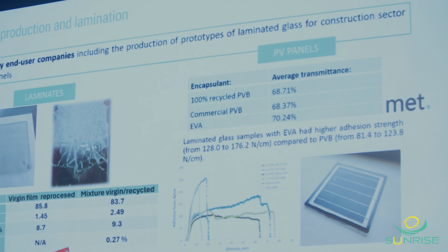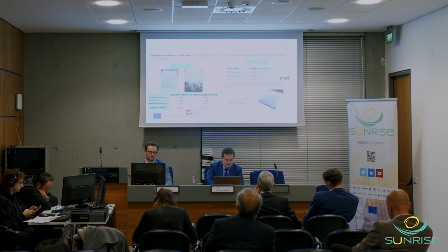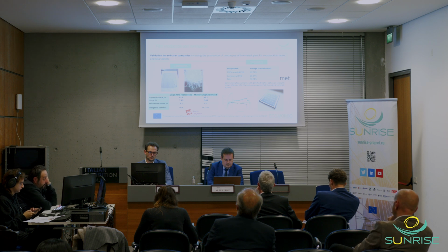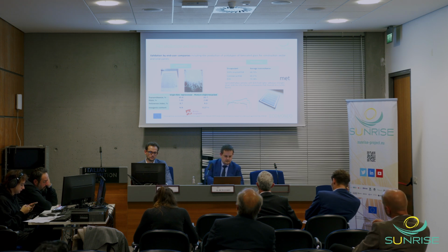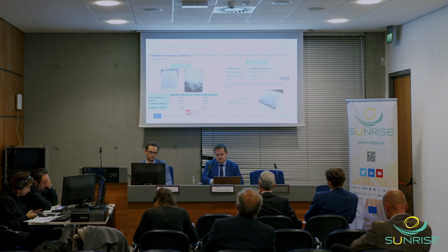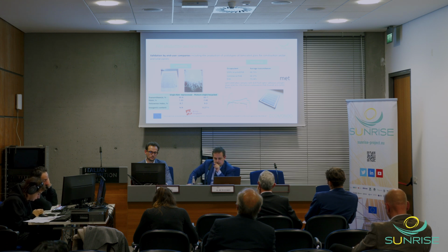But when we compare this with the virgin PVB without reprocessing, what we see is that most of the increase in haze, most of the worsening of the properties, is due to the reprocessing of the materials, which also can involve some impurities in this reprocessing. I mean, we are not working in clean conditions when we make these films, so this is something that can affect. What I want to say here is that these values are not bad at all, because if we could translate this to a real production facility of PVB with good facilities in terms of extruders and film and gas extrusion machines in clean conditions, this could be even better.